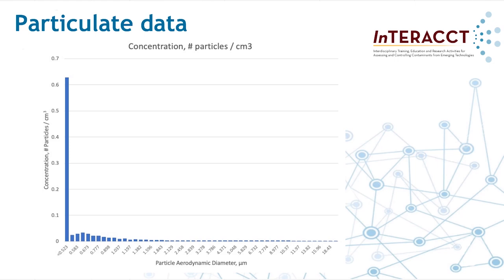I would like to offer a supplement to the integrated personal samples shown here. Simultaneously, particulate data was collected during the process using real-time detection instruments placed on the bench beside the printer. These instruments were able to detect particles with aerodynamic diameters between 10 nanometers and 20 microns. You can see by the graph shown here that although the integrated samples revealed air concentrations that were very, very low, there were still particles being emitted, and those particles were almost entirely very, very small.